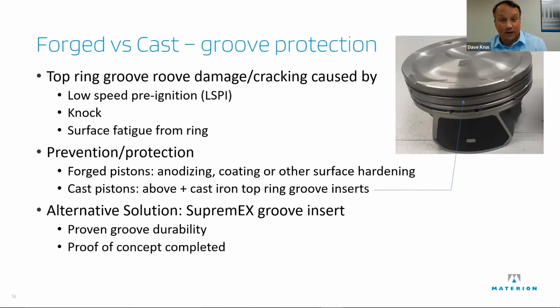But if you don't, you've got a very limited life with a 4032 or a 2618 or even the cast hypereutectic. For the cast pistons, you can put in the ring groove insert, right? But there's a penalty that comes with that. It's heavy and it doesn't conduct heat very well, right? So one of the things we came up with is the Supremex groove insert. We've already proven the groove durability. It works in that durability test at Cosworth. It's worked in other durability tests. And we did do a proof of concept on it that I'll show you next.